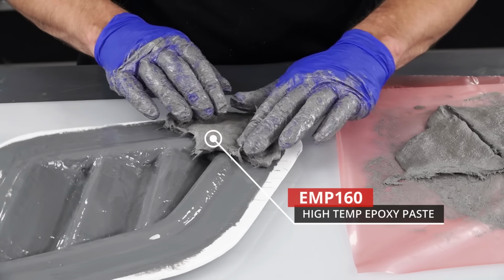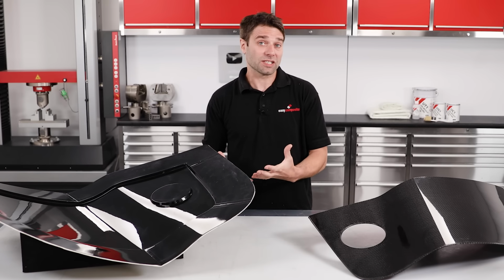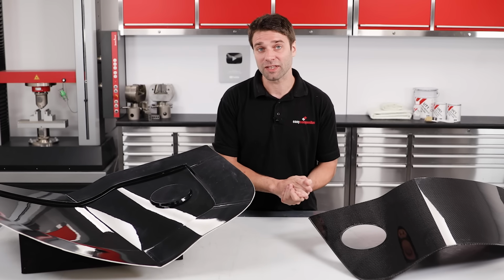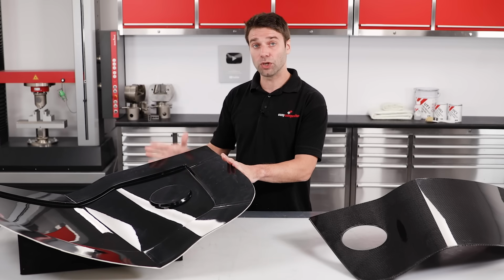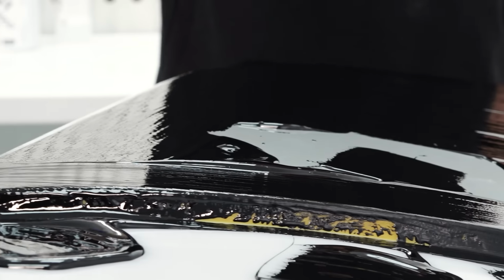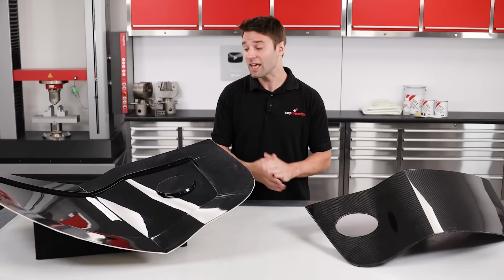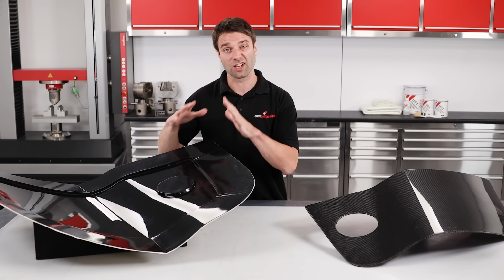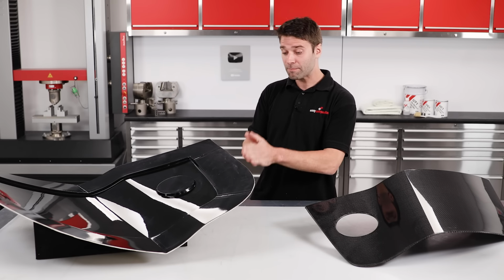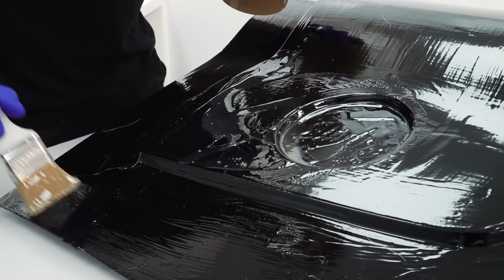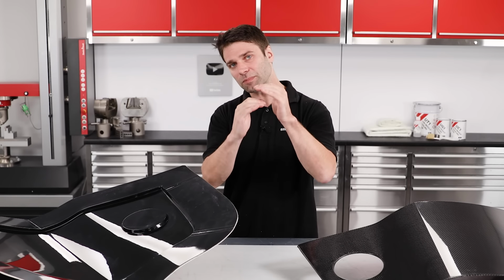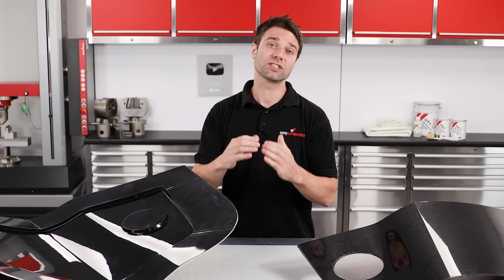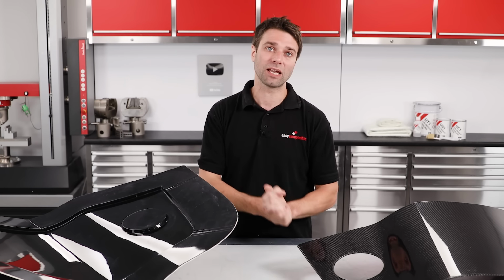more suitable. Working with Uni-Mould is very much like working with traditional fiberglass mold materials, but it does differ in a few key ways. Firstly, it has a highly durable and polishable vinylester gel coat, which, unlike traditional polyester gel, offers excellent release performance with epoxy resins, and it's also less prone to scratching and cracking. This gel coat is then backed up by a high-performance vinylester coupling coat, and this creates a seamless bond with the gel and also minimises the risk of getting air entrapment between the plies.